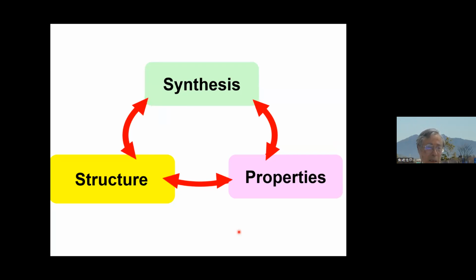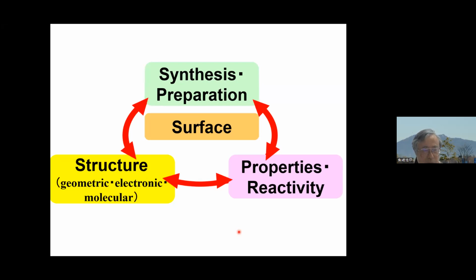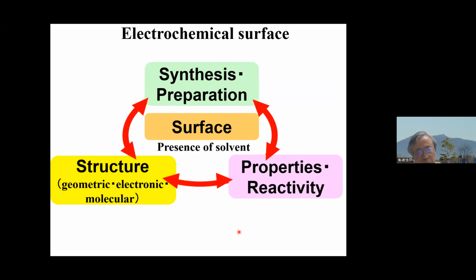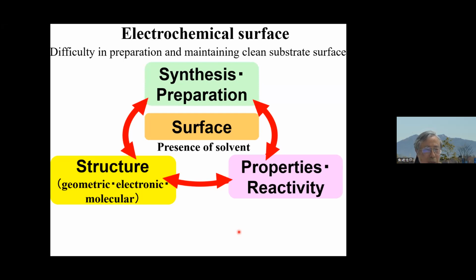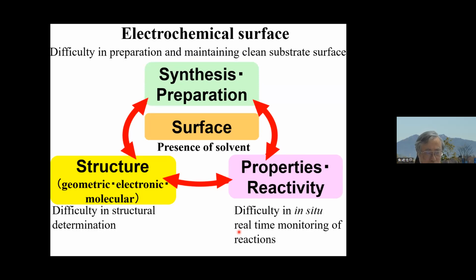Generally in chemistry, we learn that the relations among synthesis, properties, and structure are very important. In these electrochemical reactions, of course, the surface is involved. So the preparation of the surface, surface reactivities, and also structure, including geometric, electronic, and molecular structures. Particularly in the case of an electrochemical surface, the presence of solvent makes the situation more difficult. It is very difficult to prepare and maintain a clean substrate surface in solution. And also, of course, to measure the property or reactivity in situ in real time, and the structure determination is difficult within solution.